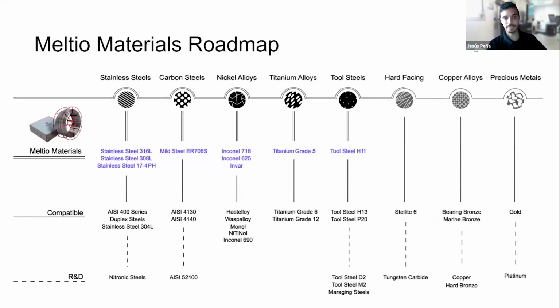We have broadly printed several stainless steels overall. We have also focused on some carbon steel, like mild steels, ER70. We have also printed several nickel alloys. Titanium alloys are fully compatible, hard-facing materials. We have already tested them with a really good printing process, also with copper alloys. And of course, this is not something that we just stop at. We are keeping on developing the technology. We have several new features that we are adding day by day to our technology.